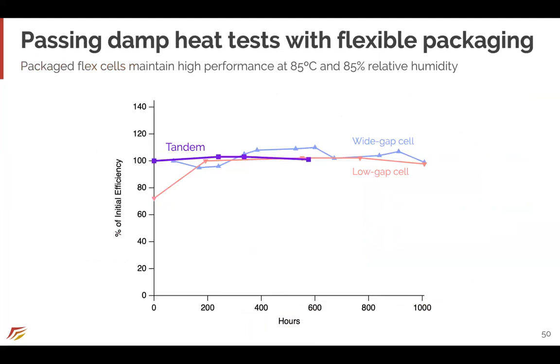So at Swift, just to give you an example, we've been able to pass damp heat tests with flexible packaging. So this is just over 1,000 hours, the efficiency change for tandems and wide gaps and low gaps. And obviously going for these flexible applications makes stability more challenging. You can't just use glass as a barrier, but we are making very good progress here.